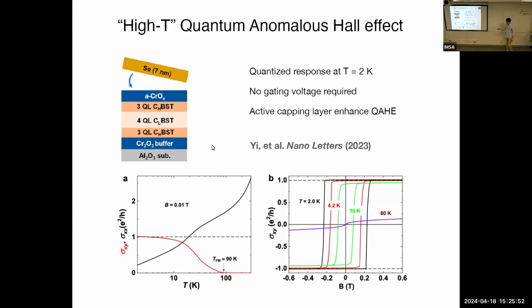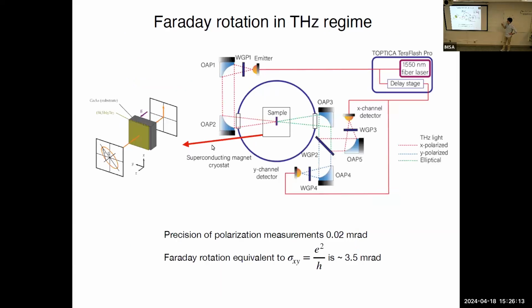After seeing this result in the normal DC Hall transport measurements, we decided to look at the optical response, because there was a precedent that optical response was actually better than DC transport, as I showed in the case of bismuth selenide. We did that, and before I show the results on the magnetic case, I just want to give theoreticians and mathematicians some sense of how these measurements are done, especially this optical measurement. As I said earlier, you hit a slab of 3D topological insulator with linearly polarized light, and then you measure by how much its polarization has been rotated.